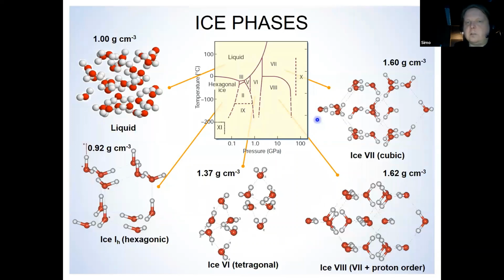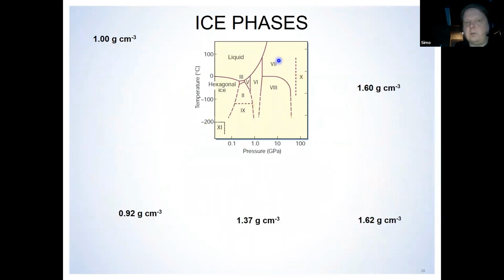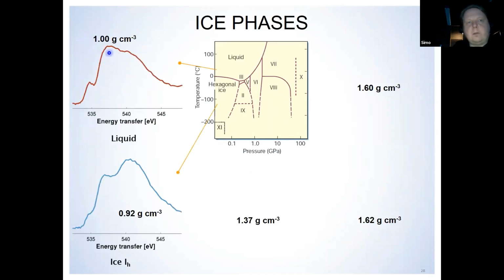So there's a lot of controversy, and at that time when we did this study, it's some time ago already, and a lot of new things have happened since then, but nevertheless, some of the controversies was, for example, is the proton order one of the key things that affect the spectra. So we wanted to take a look at the spectra of these ice phases, and now you can do that with X-ray Raman spectroscopy with the diamond anvil cell. So it turns out that these are the ambient pressure phases. This is liquid water with 1 gram per cubic centimeter density. It has this pre-peak, main edge,